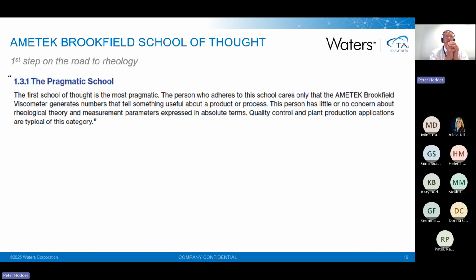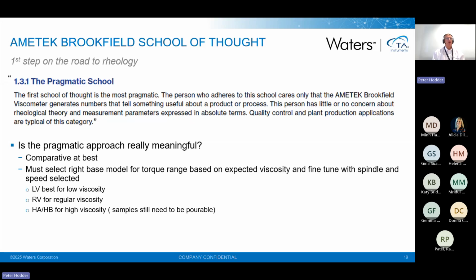So what I want to point out there is, for the first step on the road, the pragmatic approach, according to the booklet and everything else in Brookfield, what you're looking at realistically is a comparative method at best. You have to choose the right base model to start off with to ensure your sample actually remains and can be measured with the torque range available. You might fine tune it by choosing the spindles and the speed selected, but basically you're going to be, for low viscosity, using the LV, for regular viscosities, the RV, and for the stiffer materials, the HA or HB. Now there are other things we're going to talk about later, but very simply,